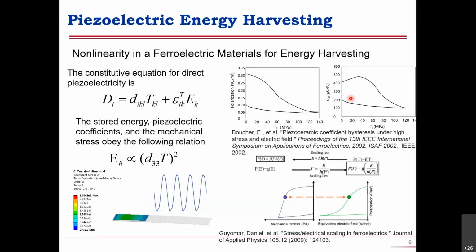According to this, it will lead to the d33 decrease. Even if we take away, release this mechanical stress, the d33 will have a decrease on this value. It can't come back to the original value.